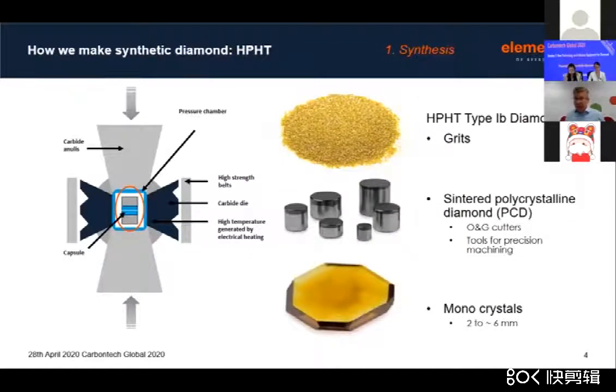So as said, 1951, I believe, HPHT diamond was developed, high temperature, high pressure, and as you all know, most of the diamond that's produced by HPHT is type 1B diamond, which has got a large amount of nitrogen in it, and it's possible to make grits, PCD, and monocrystal diamonds. And as you can see, those can be quite large, but effectively there's an awful lot of defects and extended defects in those materials that it's very, very hard to eliminate.